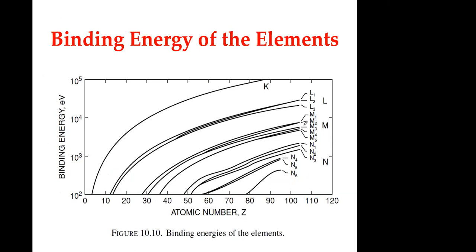I showed this before, the binding energy changes with atomic number. The cross-section I showed before is different, but the binding energy also changes depending on the element. So the level K 1s 1/2 changes with atomic number. As you increase the atomic number, the binding energies are higher for the K level, L level, M and the different N levels as well. So as you increase the atomic number, the binding energy increases. So you can follow that very easily.